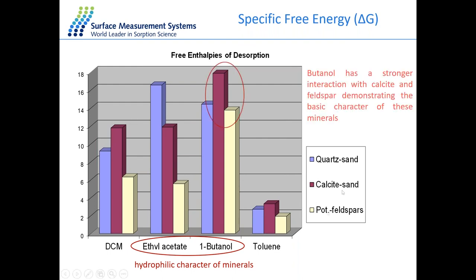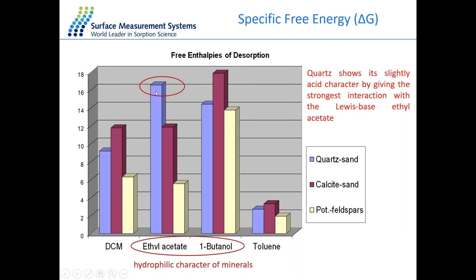And in case of the specific free energy, which is the interaction between the polar molecules, all the mineral materials have a very strong interaction with ethyl acetate and 1-butanol, and this indicates the hydrophilic character of all the mineral samples. In case of the calcite sand sample and feldspar sample, they have the strongest interaction with 1-butanol, which is a kind of Lewis acid solvent. That means those two samples have a basic character compared to the other minerals. And the quartz sand sample has the strongest interaction with the Lewis base solvent, which is ethyl acetate. That means this sample shows slightly acidic character compared to the other samples.